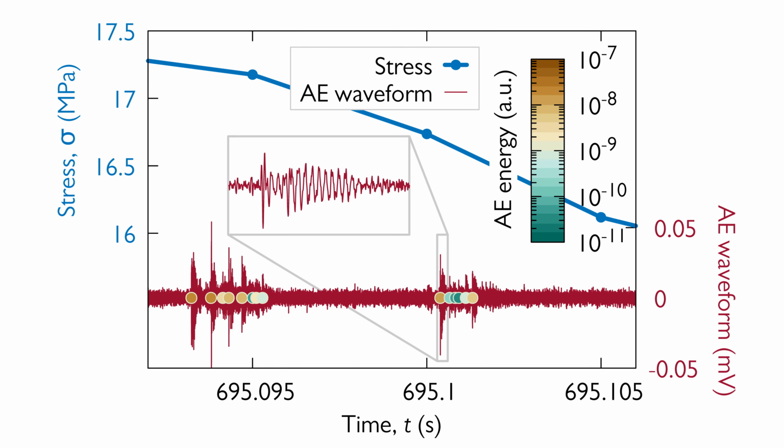A larger zoom shows that the acoustic emission signal consists of short peaks standing out from the background noise. We thus conclude that the acoustic emission events are indeed due to the dislocation activity leading to plastic slip of the micropillar, whereas the intermittency of the acoustic emission bursts suggests that a single stress drop is a result of complex internal dynamics on timescales not accessible by stress measurements.